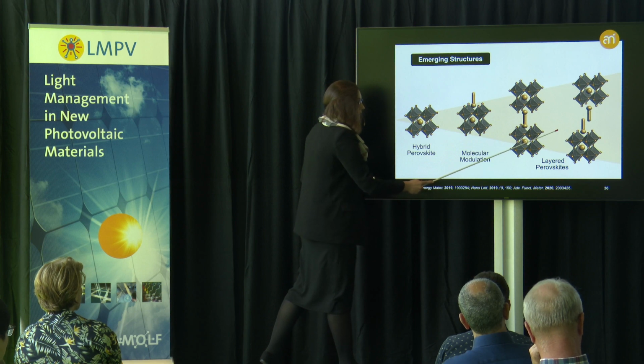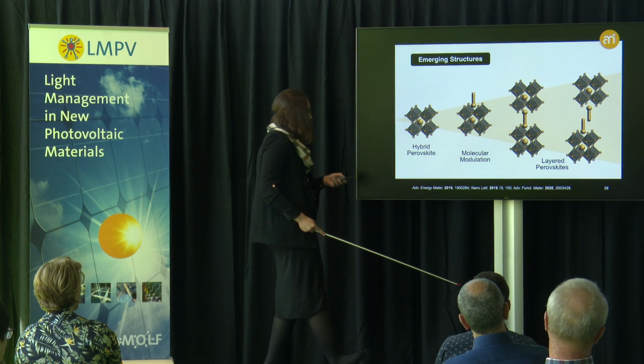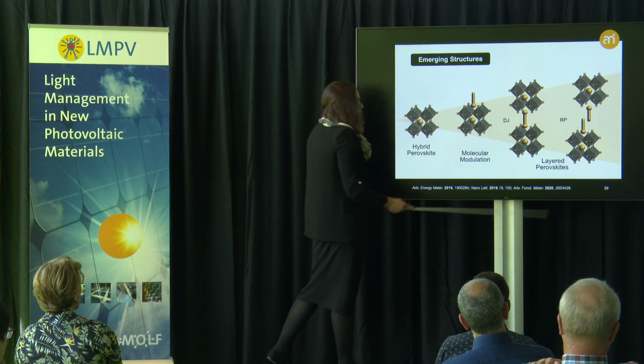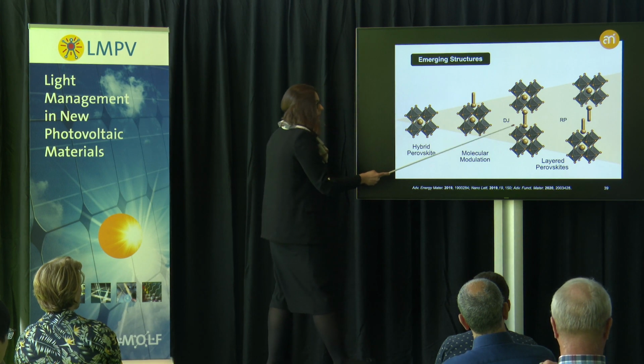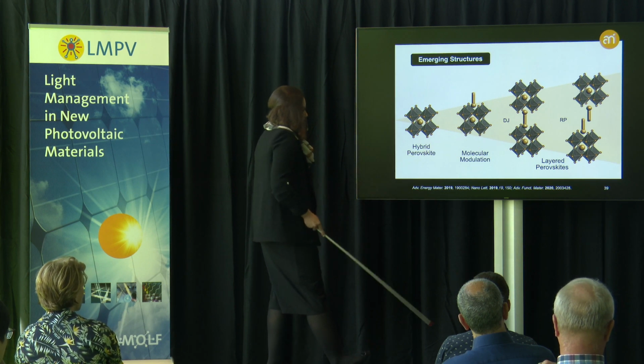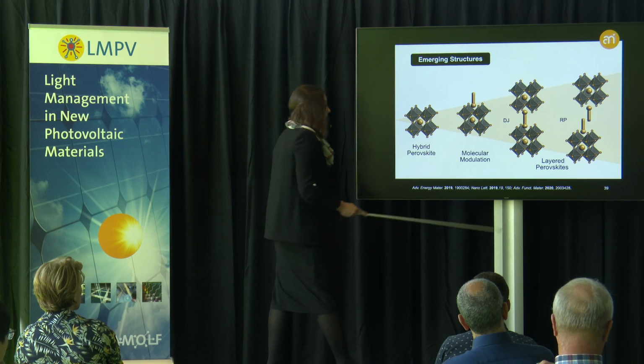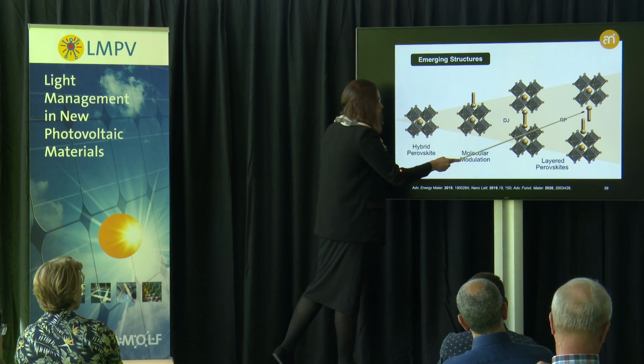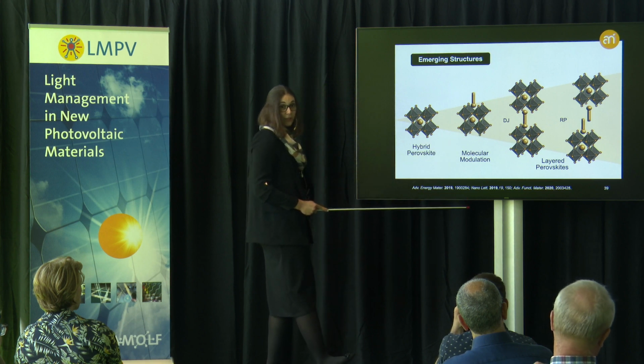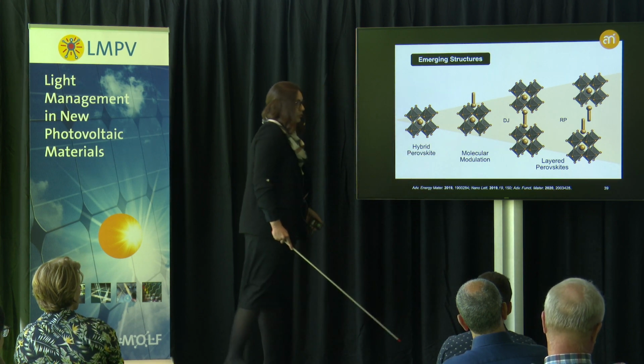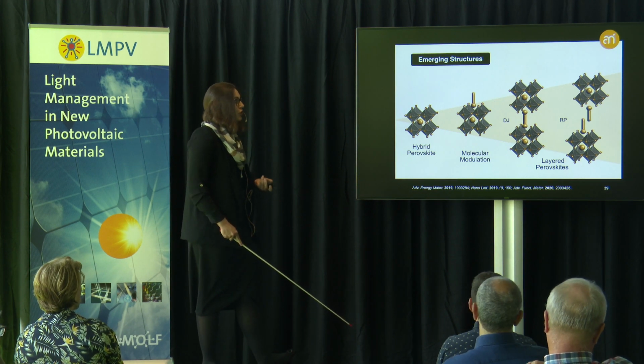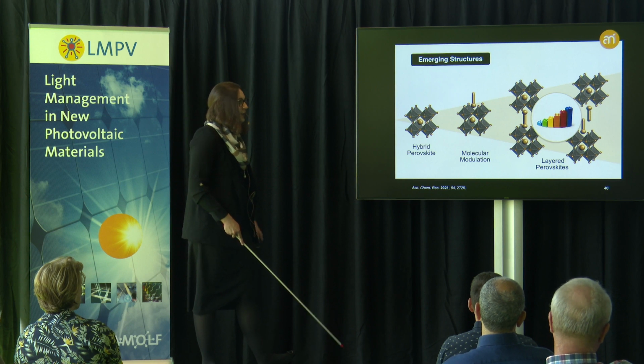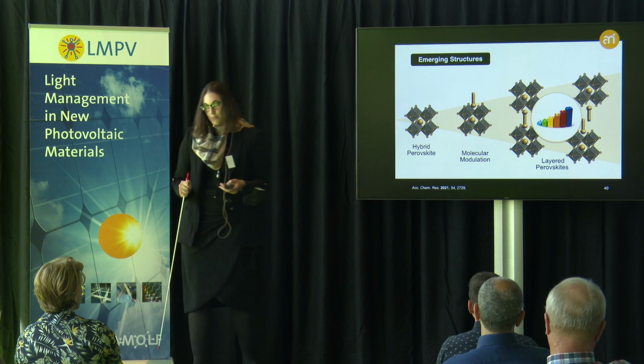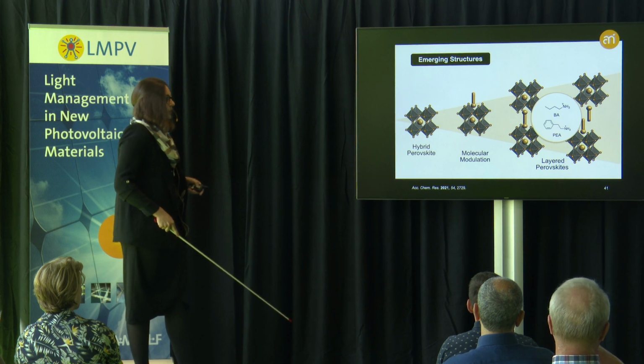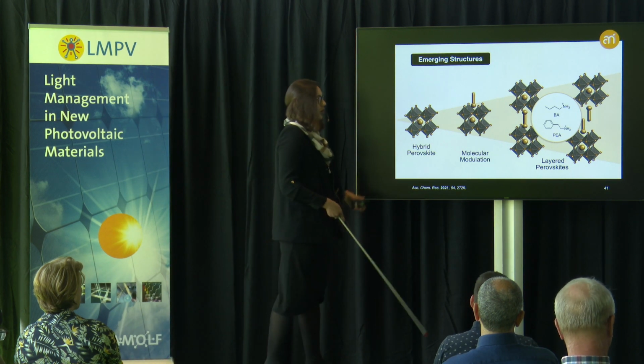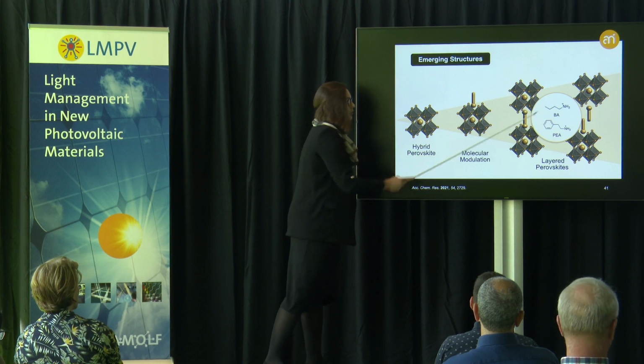the perovskite architecture and further contributing to its stabilization in different types of perovskite architectures, either these monofunctional so-called RP or a monolayer bifunctional system, better known as Dion-Jacobson or DJ architectures, in both of which cases stabilizing the system through increasing the hydrophobicity of the organic phase, as well as its ion impermeability, which also opens the possibility to tailor further the optoelectronic characteristics of these systems more directly by controlling the assemblies of the organic components, which is something that I would also briefly like to illustrate in an example which so far challenges the two typical examples that have been used in the literature so far